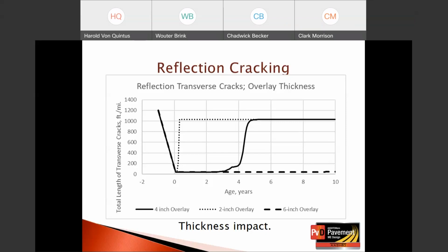The 4-inch, which is the solid black line, it takes longer for those cracks to propagate, about an additional 2 years for the cracks that are there in the existing flexible pavement. And then they don't start to occur, or we don't start to see them at the surface, until a longer period of time, obviously. The 6-inch asphalt overlay is the longer dashed line, and that shows that basically, within a period of 10 years, for only 10 years, it prevents any significant reflection of the existing transverse cracks from the existing flexible pavement through a 6-inch asphalt overlay. The overlay thickness is very important for fatigue and transverse reflective cracks.